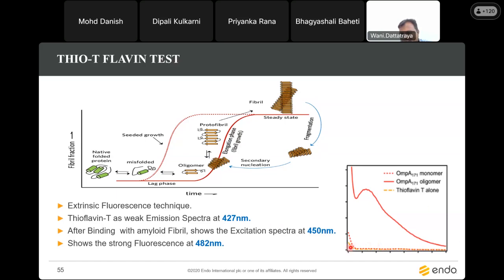This is the fluorescence spectra of only thioflavin T. You are not seeing any intense peak. The second spectra is only monomer. Thioflavin T will not interact with the monomer, and will not show any intense peak. If there are oligomers or fibrils, it will interact with the thioflavin T, and you will get some emission, a broad spectra, or absorbance here. So based on that, you can conclude that there is a formation of fibrils in your molecule.